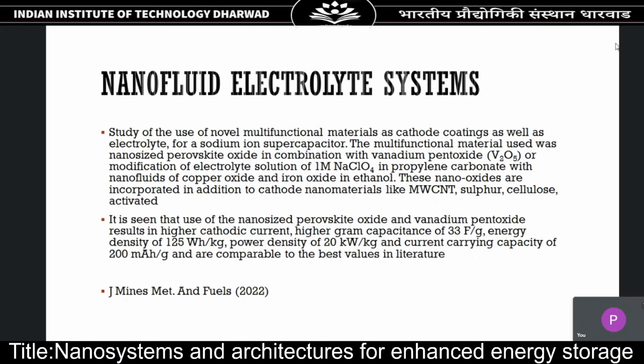So next, going on to nanofluid electrolyte system. One of the devices we are currently studying is a sodium ion supercapacitor. Normally what is used in the sodium ion supercapacitor is sodium perchlorate in propylene carbonate as the electrolyte. So we modified that electrolyte with nanofluids of copper oxide and iron oxide in ethanol. And of course, the electrodes of the sodium ion devices are themselves made up of nanomaterials like carbon nanotubes, sulfur, cellulose, activated carbon, etc. We were able to get very good values from using nanofluids.